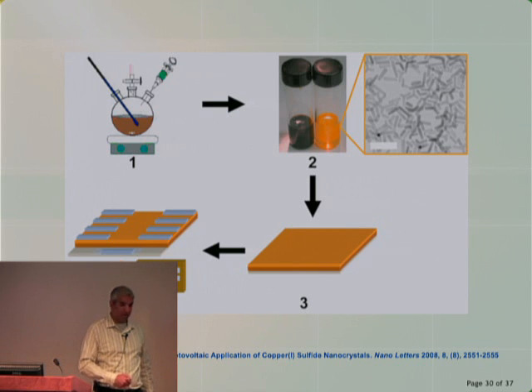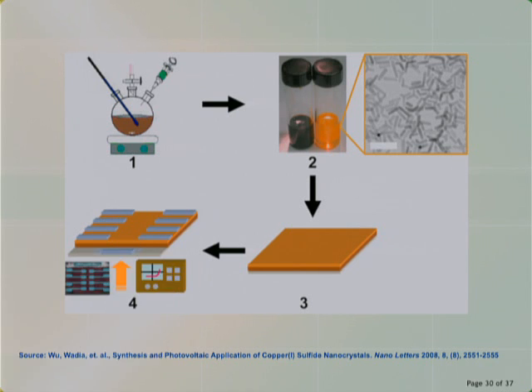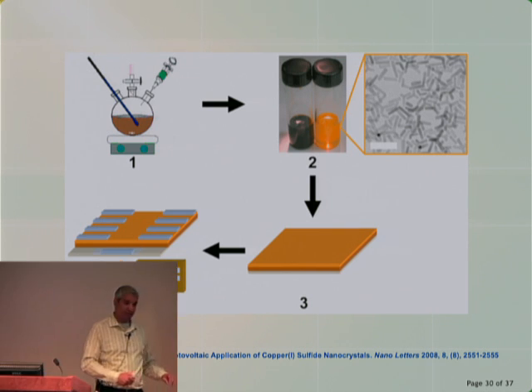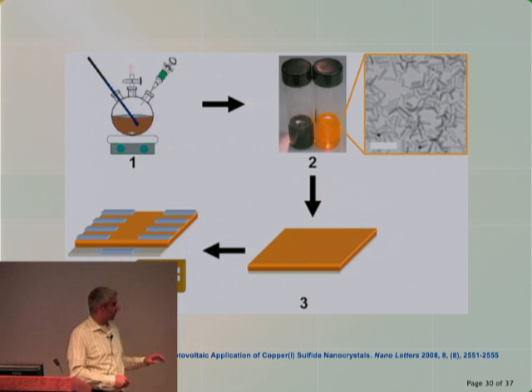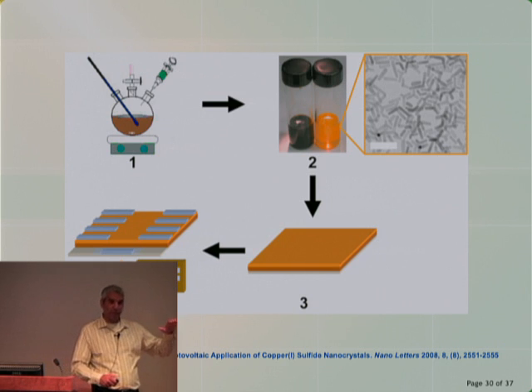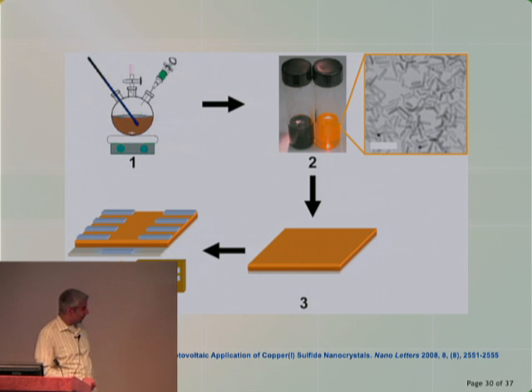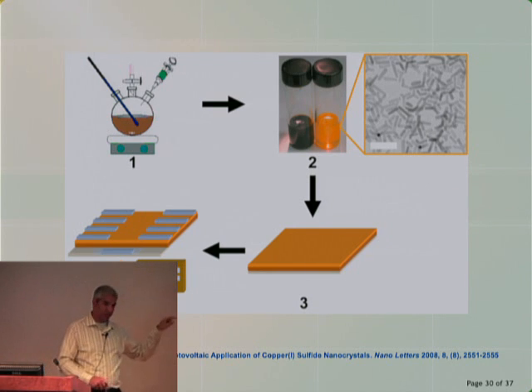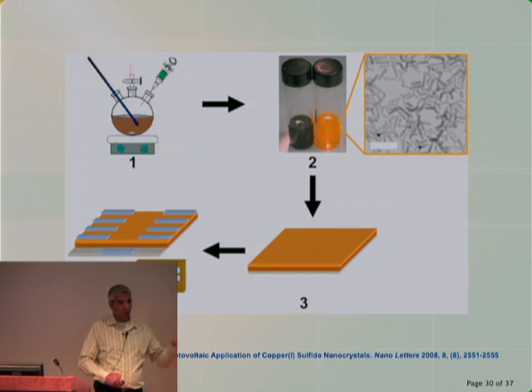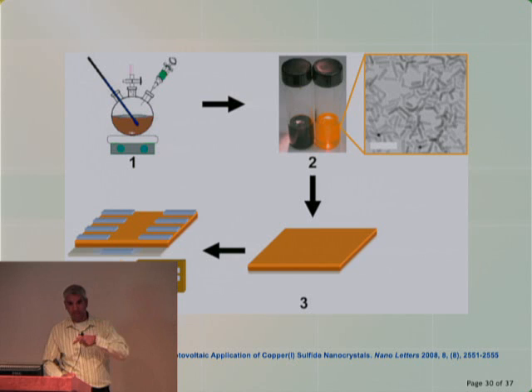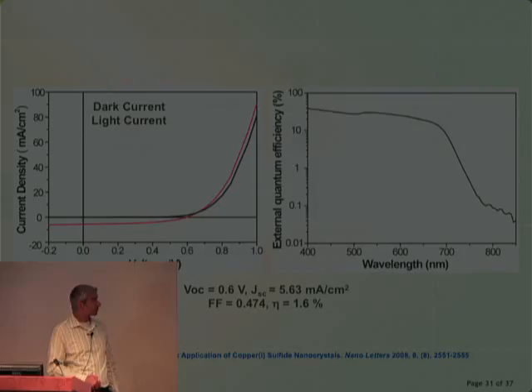We put down some copper sulfide, low temperature anneal it, about 150 degrees for 5 minutes. Then we put down cadmium sulfide on top of that, do a small anneal, and then these are our contacts. Each one of these is thermally evaporated, and the end result is a chip that looks like this. It's 1 square inch, very small, and each of those aluminum pads represents an individual solar cell. So when we test it, we have 8 solar cells that we can cycle through very quickly. But this is basically how we're doing our work.